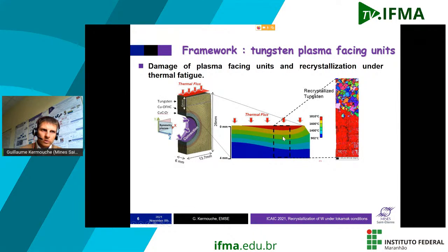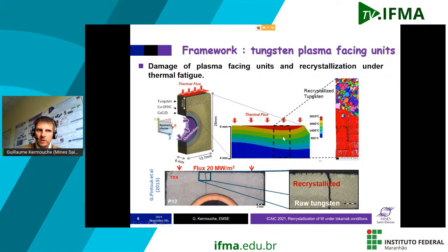And so if you look at what happened to the monoblocks in terms of damage, you can see a crack that will propagate from the surface to the copper tube here. So this is something that matters, because if there is a crack and the plasma enters into the crack and goes to the copper tube, there will be melting of the copper. So there will be some issue with that. So we have to prevent this crack. And what we know is that this crack is finally driven by the recrystallization.